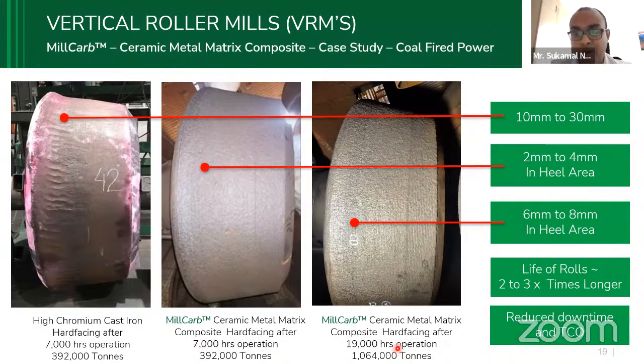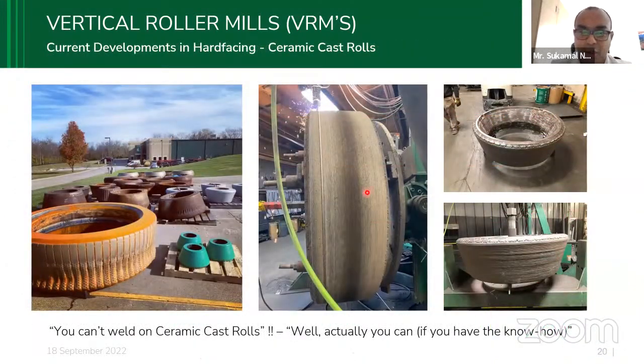Now the same component we further used in operation, and after 19,000 hours with 1.06 million tons of production, we can still see that only 6 to 8 millimeters has worn out. So depending on the requirement, we can enhance the life of this kind of component. These are rollers which were all put in the scrap, and we took them back, rebuilt them, and put them back into service.